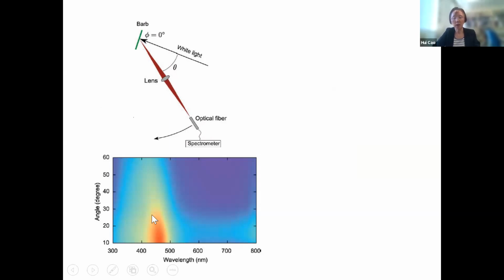So again, this shows the horizontal axis, which is wavelength, and the vertical axis, which is the angle of observation, theta. The red color shows the reflection peak. You can see the peak actually changes slightly with the angle. That's because we fix the input and try to see the light from different angles. If you always see from the back, it is the same color. But this very tiny shift is fairly small. That is what Raman noticed, and that's why he thought this must be coming from an interference effect.